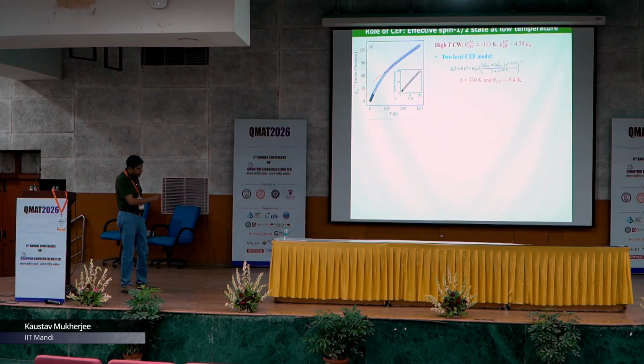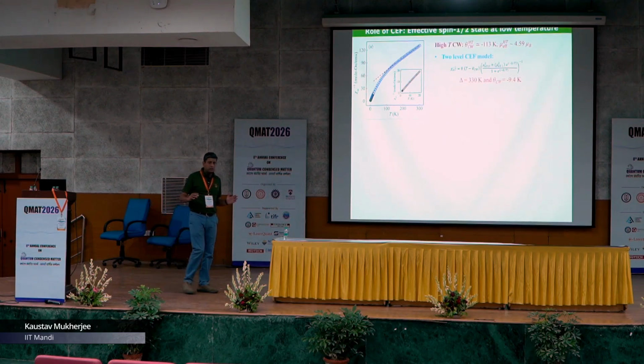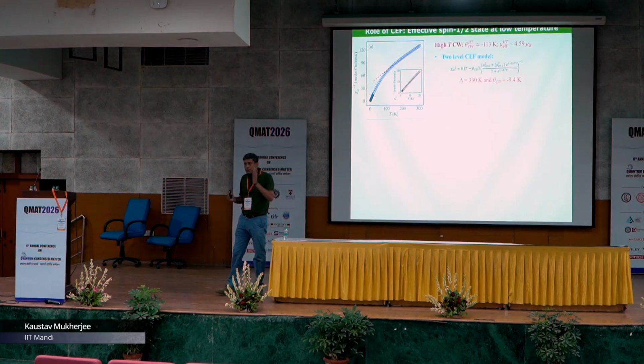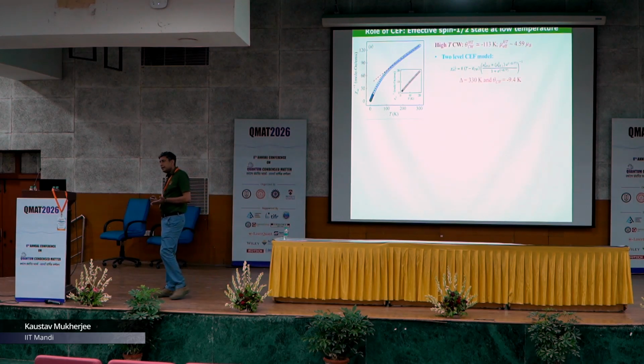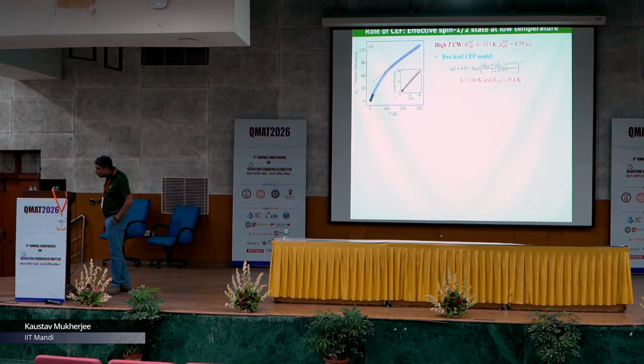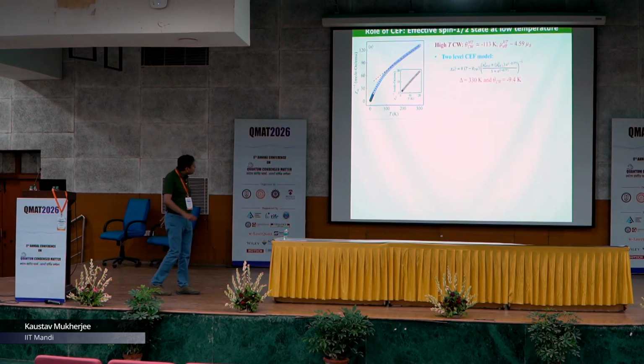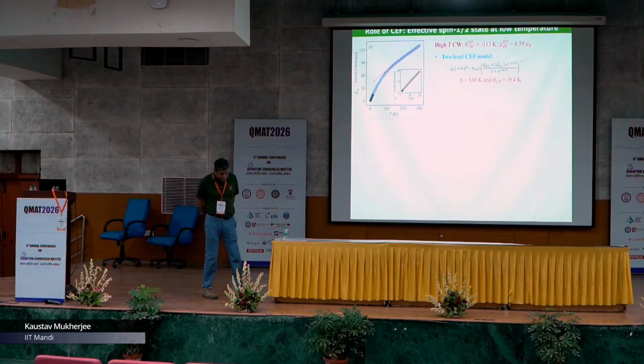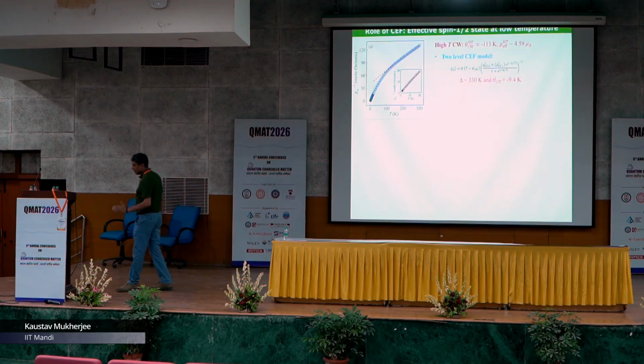Now here we see a deviation. Generally this Curie-Weiss law, if there is no long range ordering, should have fitted in the entire temperature range, or if there is long range ordering, above the ordering temperature range. But why is this deviation there? This deviation possibly indicates that crystal electric field is playing an important role in the low temperature properties of this compound. So we tried to fit the graph using a two-level crystal electric field model, and here the obtained delta was around 330 Kelvin, and we saw that the graph fitted well from 20 Kelvin to 300 Kelvin. Now this delta implies the energy gap between the ground state doublet and the first excited state doublet.